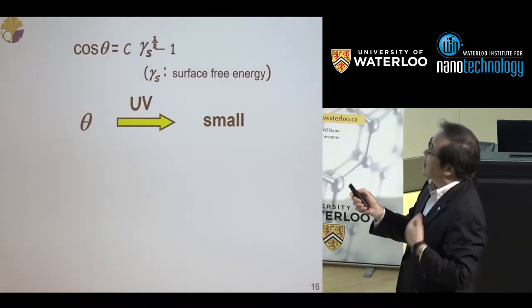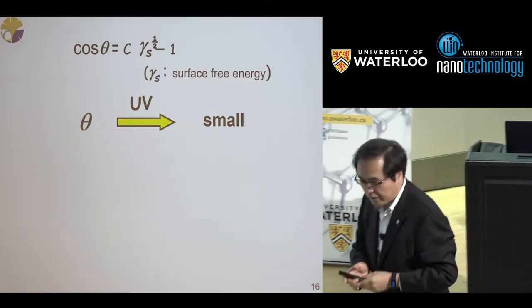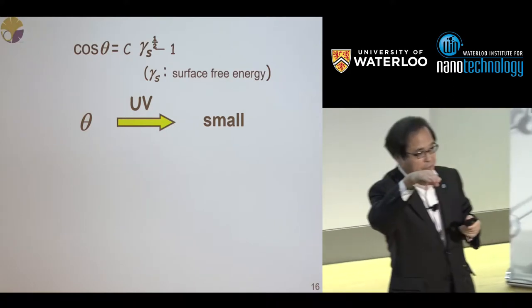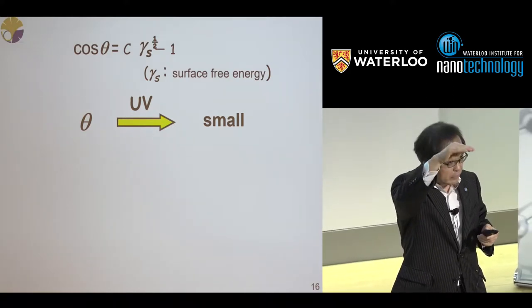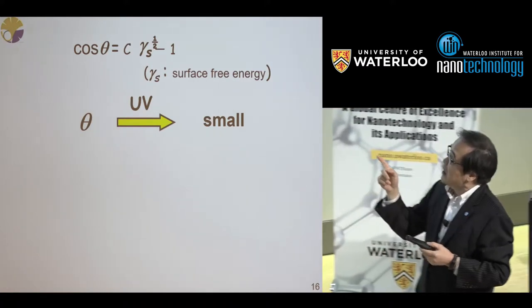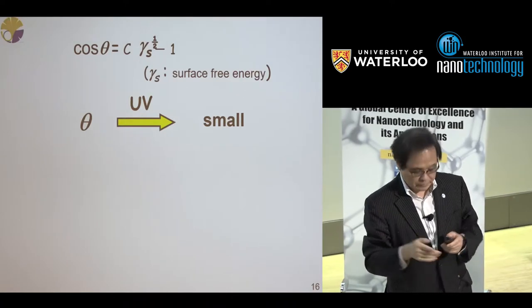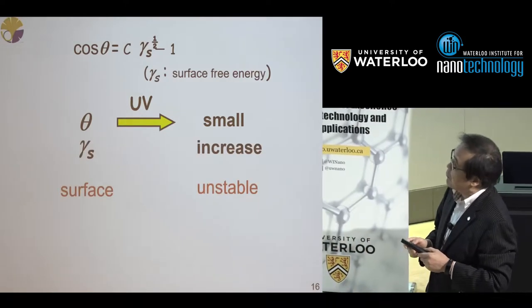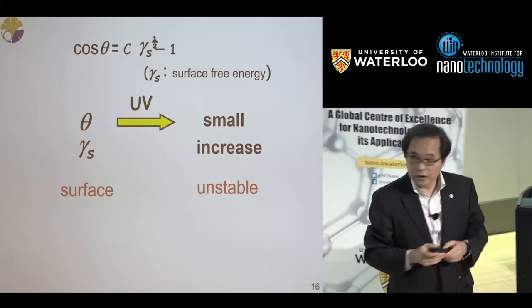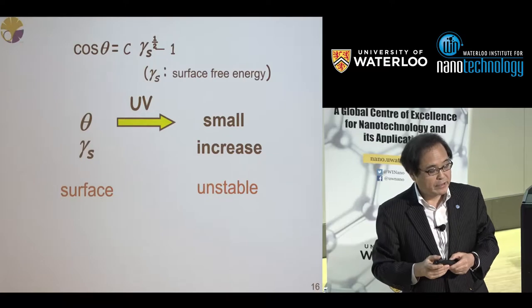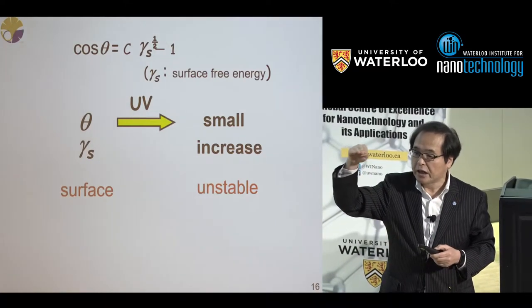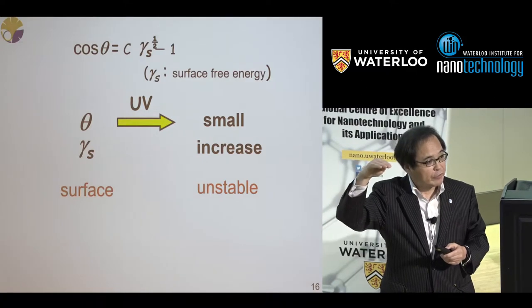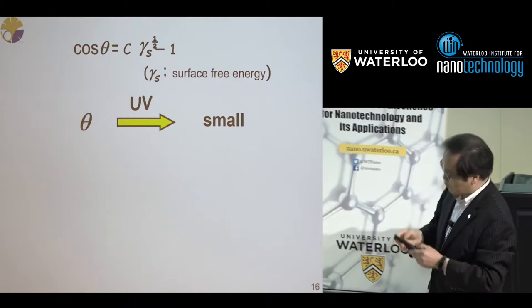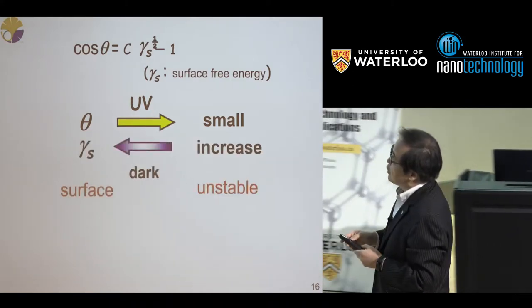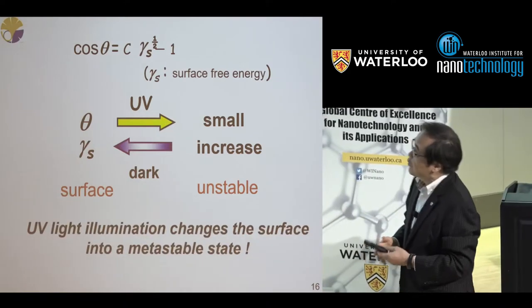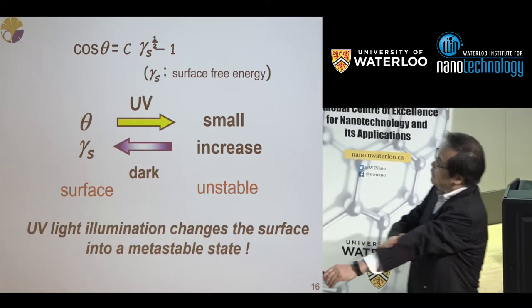The cosine of the contact angle is a function of the surface free energy of titanium dioxide, at the interface of titanium dioxide and air. So the experimental results show theta is decreasing by UV light. It means that the surface free energy, gamma S, is increasing. In other words, the surface becomes unstable by the light illumination. And such a state is maintained for several hours to 10 hours, and returns slowly, gradually, to the original one. Okay, so UV light illumination changes the titanium dioxide surface into a metastable state.